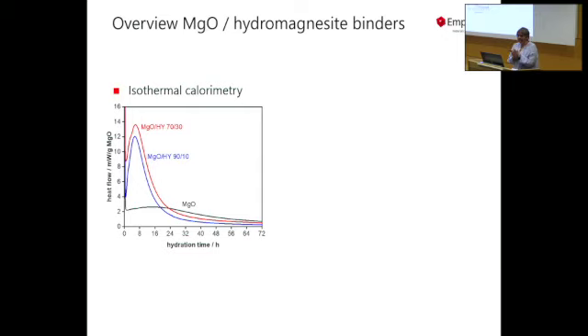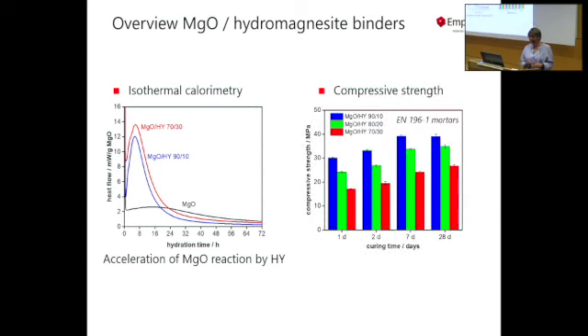And then we also thought we want to understand what's going on on the chemical side. This is an isothermal calorimetry picture. In black, you see the magnesium oxide, which goes to brucite, and it doesn't generate a lot of heat. In blue and red, you see the mixes with hydromagnesite, and if you add hydromagnesite, you get much more heat, and you also get much more strength. I did not put here the black points, which would be the magnesium oxide or the brucite, because basically they just don't produce any strength. So we cannot make brucite cement.